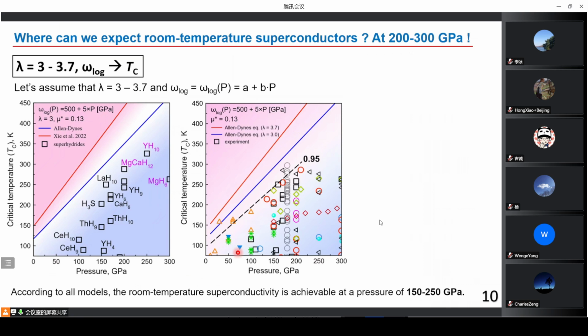And now we can use this theoretical paper and the maximum possible lambda for conventional Bardeen-Cooper-Schrieffer superconductors, from 3 to 3.7, to investigate the critical temperature of superconductivity as a function of pressure. You can see several lines. I used the Allen-Dynes model and the recently proposed Xie model. Is it correct? Yeah.